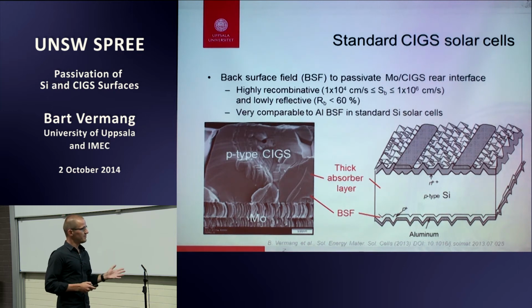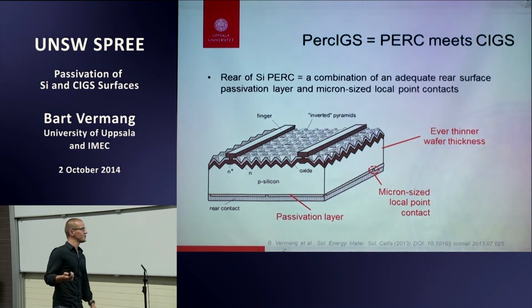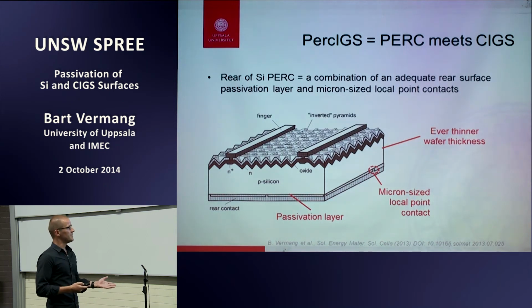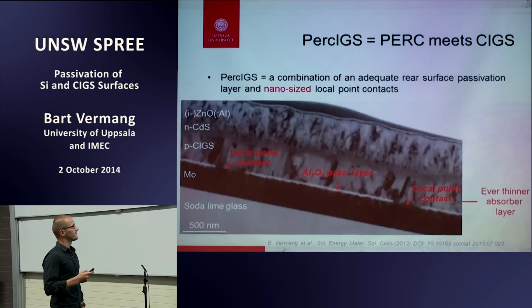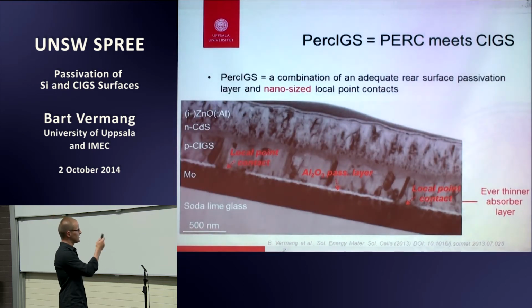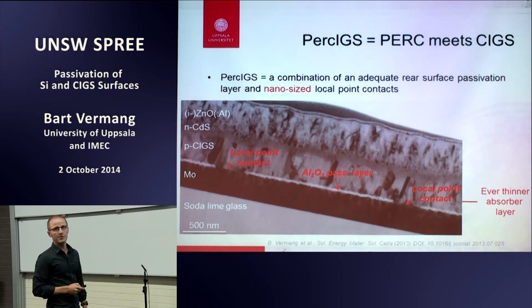Same thing, the moly is not that reflective. It's even quite poorly reflective. Very similar to a normal full aluminum back surface field solar cell in silicon. What they did in silicon, of course, and you know, they have been making PERC cells, and at the rear, what does it mean? You have a passivation layer, you have the openings. The passivation layer will passivate, so you can thin down the wafer. At the same moment, it will reflect, another reason why you can have ever thinner wafer thicknesses. So that's what we have been doing. Here again, you have the CIGS layer and the molybdenum layer, and in between you have the aluminum oxide passivation layer, and you can see some local point contacts of around 200 to 300 nanometer.